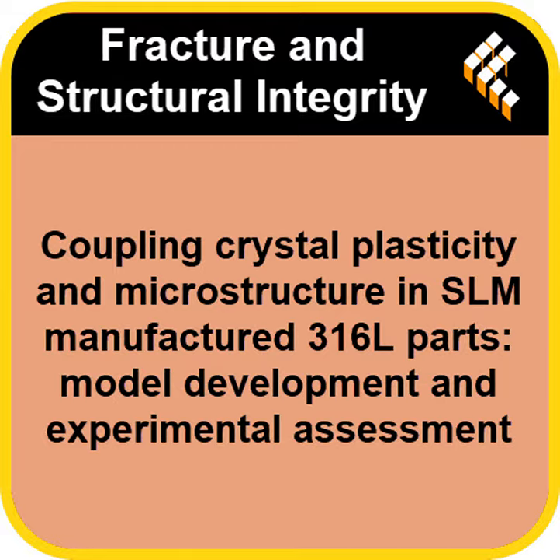Okay, so if the model knows the texture and knows where the twins are, how does it use that to predict strength? It classifies the potential paths for plastic flow, the slip systems. If a slip path is aligned nicely with an initial twin plane, that path is considered soft. It's easy to activate. Think of it as an open lane on the highway. But if the path is unfavorable, that twin acts as a hard barrier, and the model calls that path rigid.